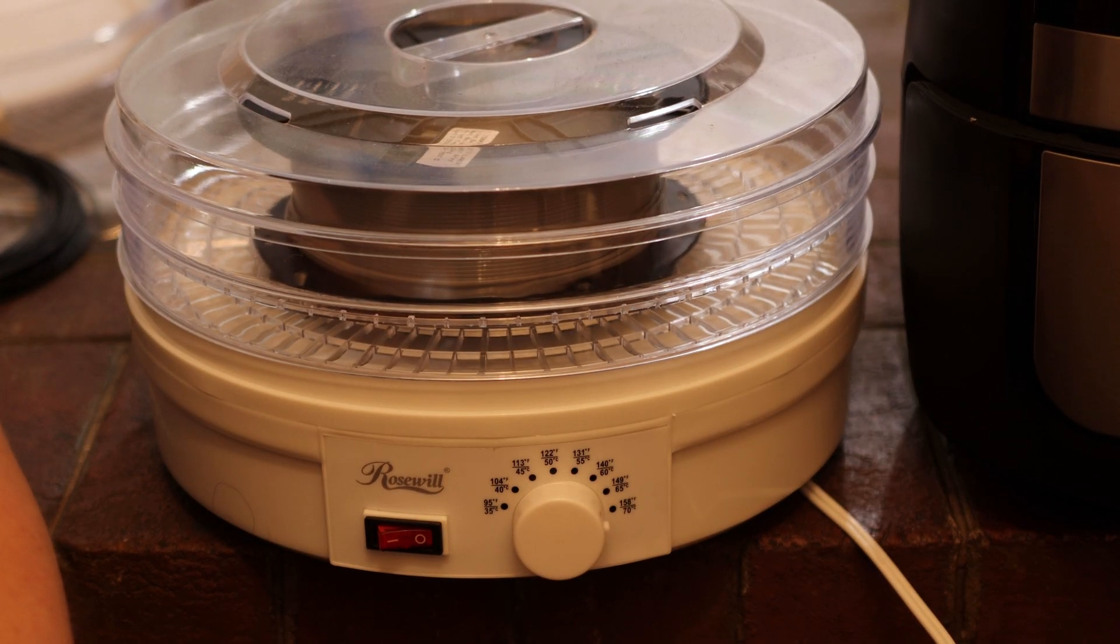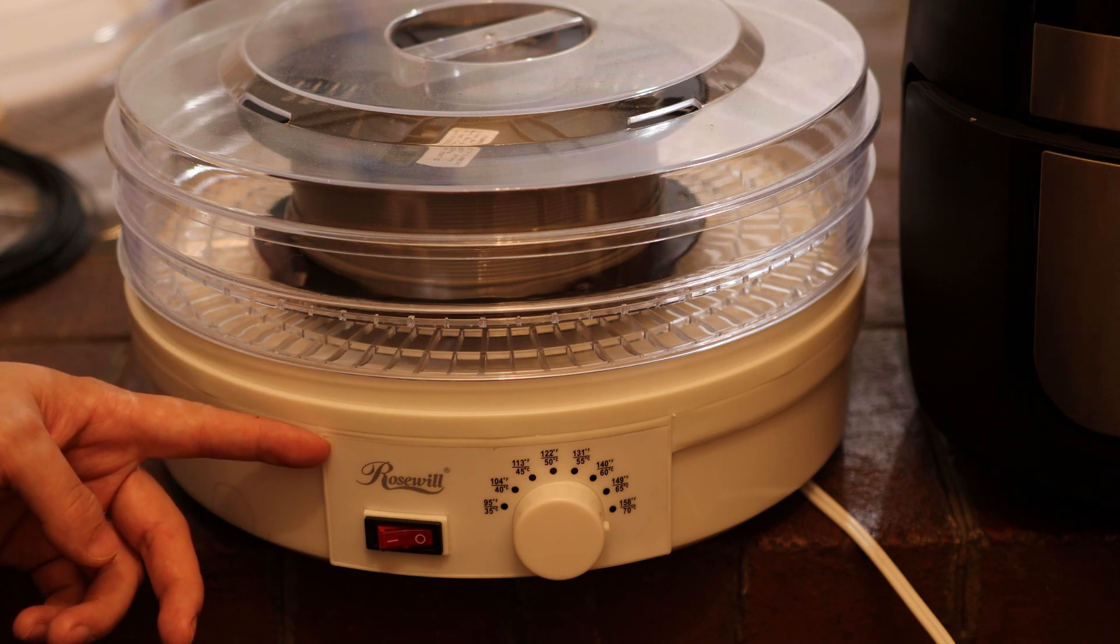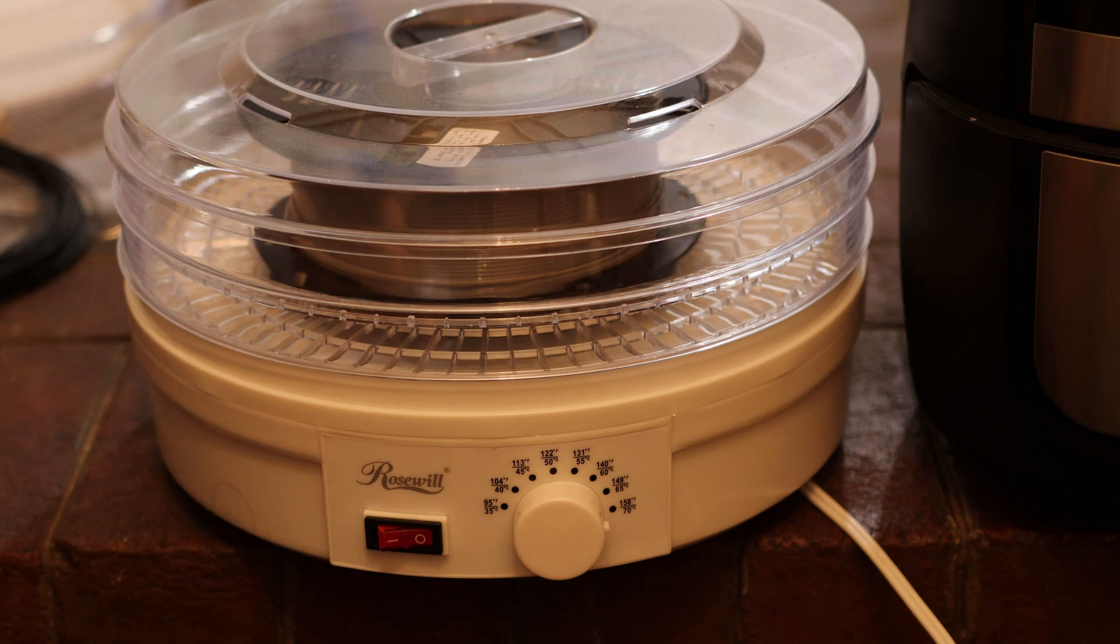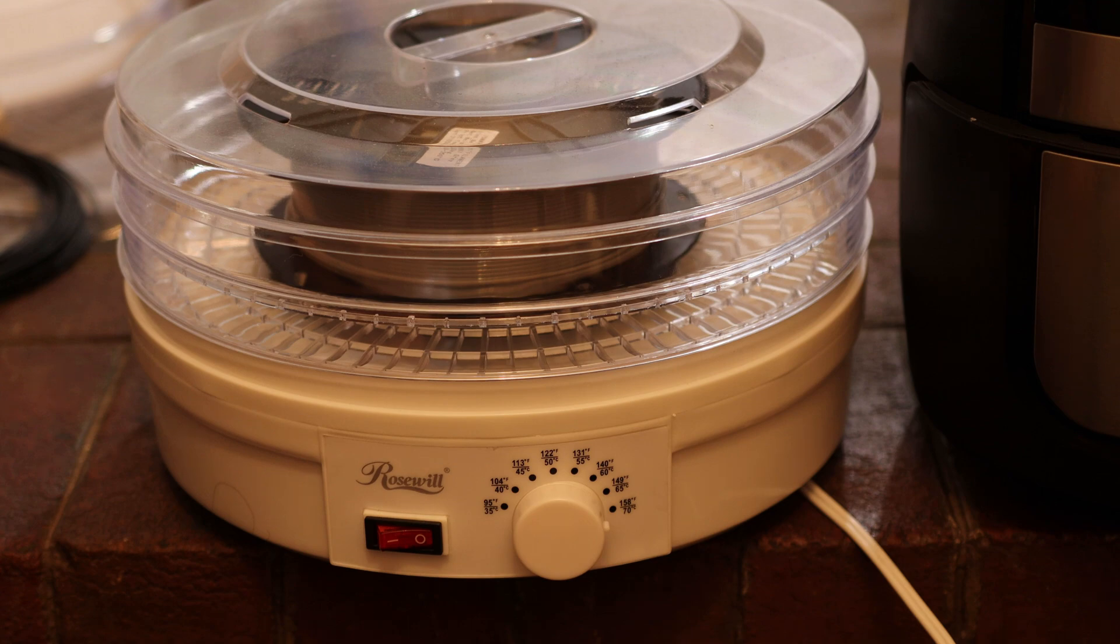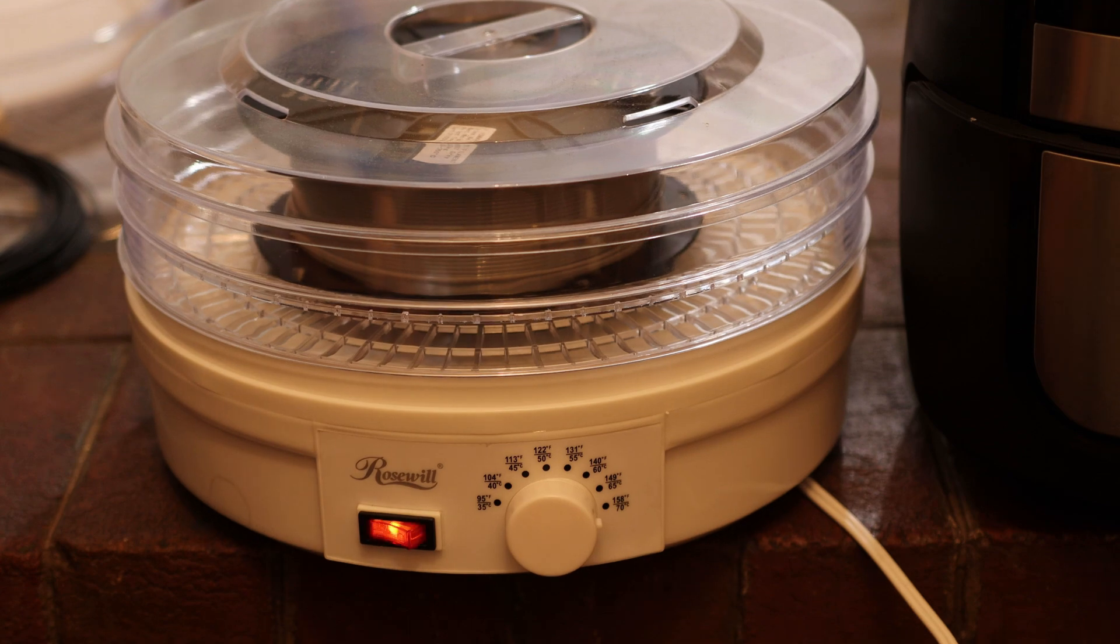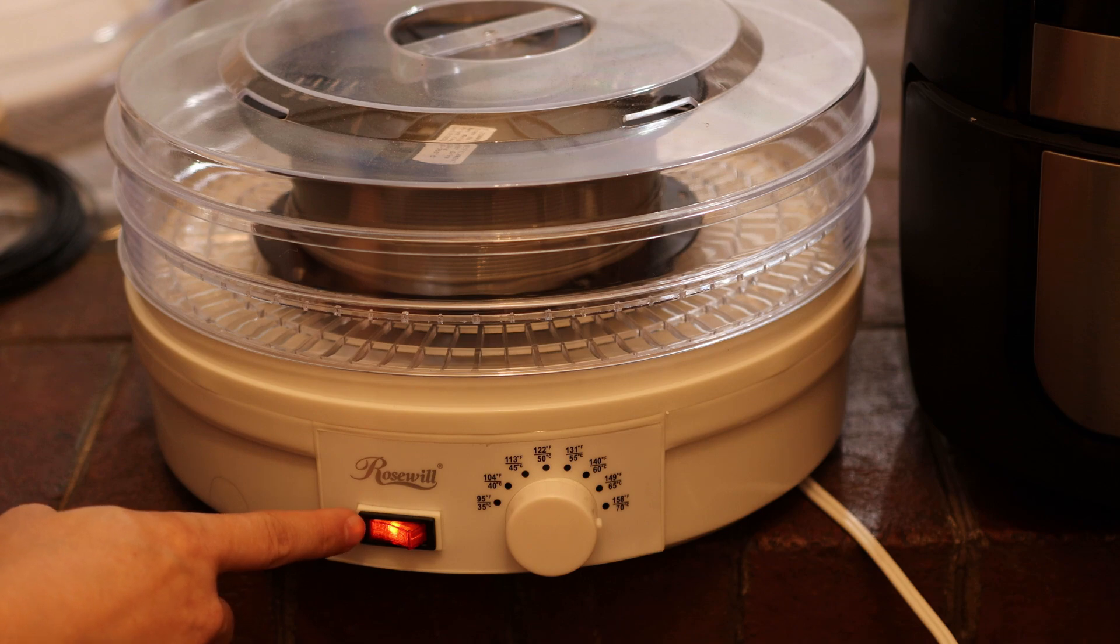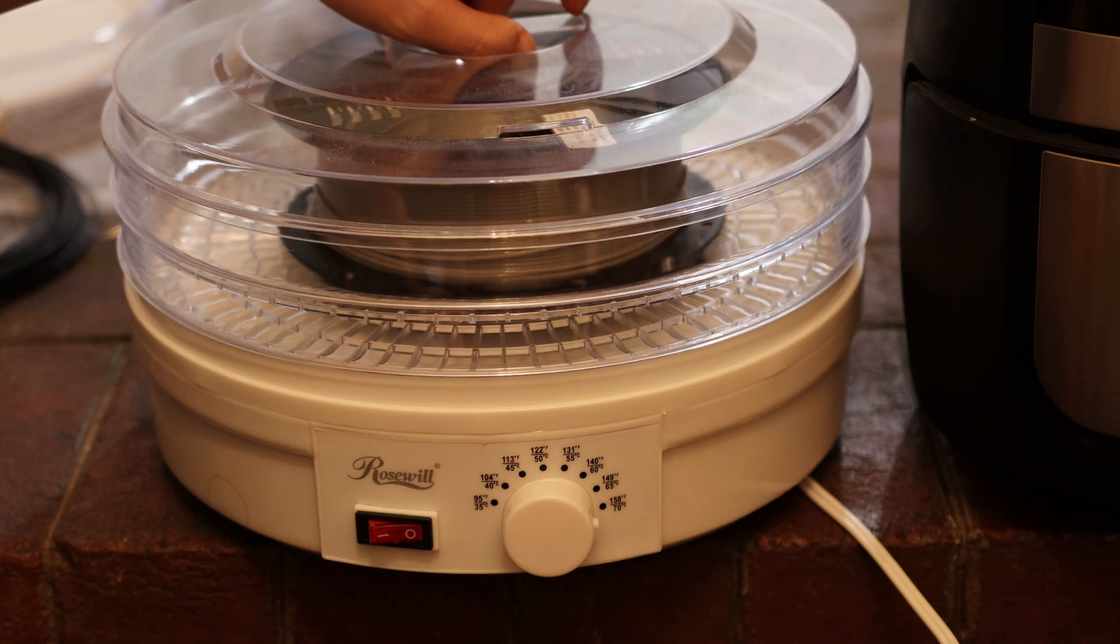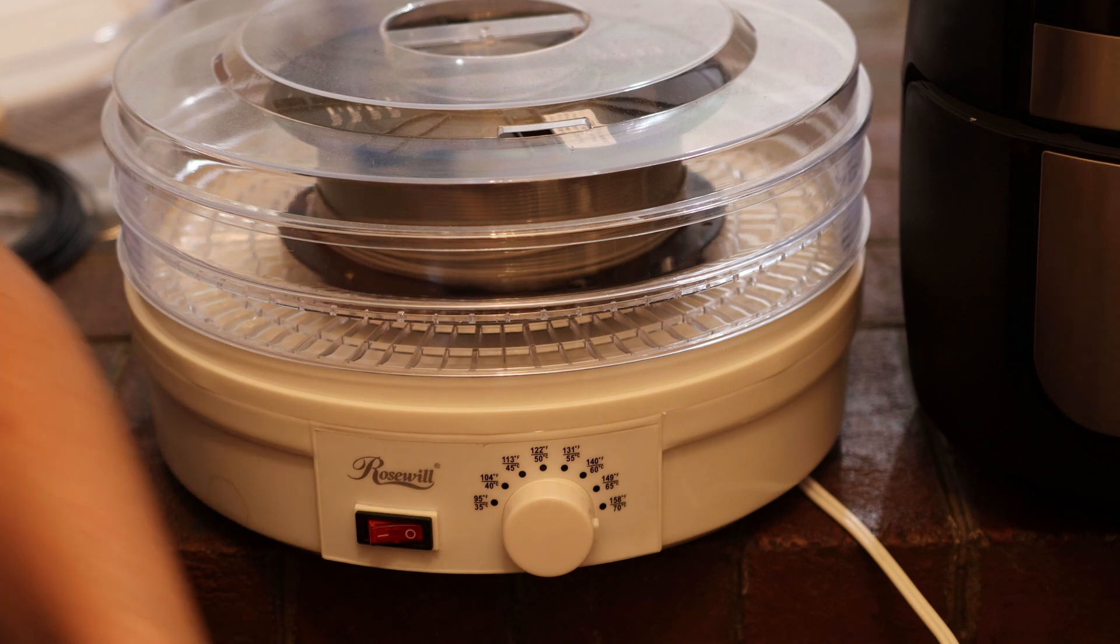What a lot of people will use to dry their 3D printer filaments is one of these - it's a food dehydrator. After speaking with SainSmart, the manufacturer of this carbon fiber filament, they told me that I need to heat it to 80 to 100 degrees Celsius to dry it out before printing. But this machine doesn't go to a high enough temperature. For higher temperature filaments like nylon, you're going to need something a little bit hotter.